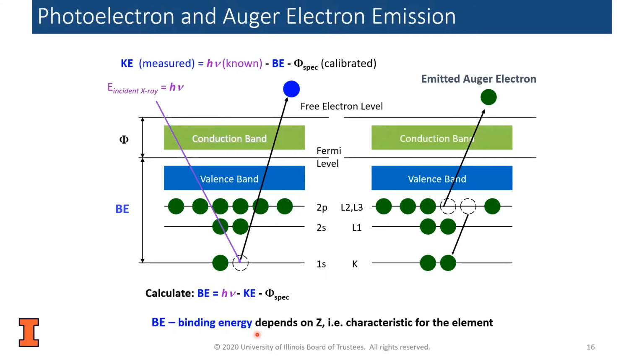Following this process, because we'll have an ion with a core hole, this ion will tend to relax and emit another electron known as an Auger electron. So on an XPS spectrum, we can see both Auger and photoelectron lines. And the complementary process to this would be the emission of an X-ray photon. This would be basically X-ray fluorescence.